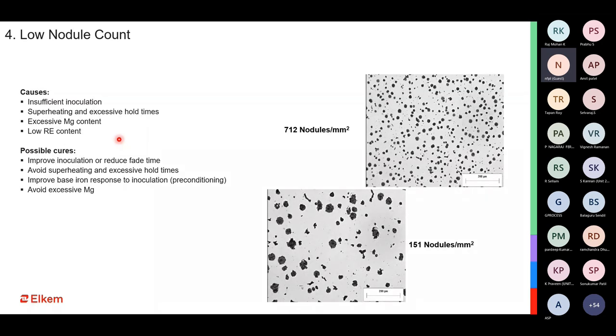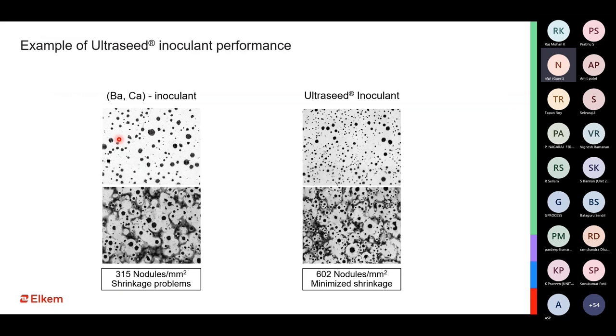Possible cures can be just to take care of all these four. You improve the inoculation, you avoid superheating, you make sure that you are able to cast in controlled time. You do not have a very long pouring time. You improve the base iron nucleation, that is by preconditioning, and you also avoid excessive magnesium coming into the system. You do not want very high magnesium in the system.